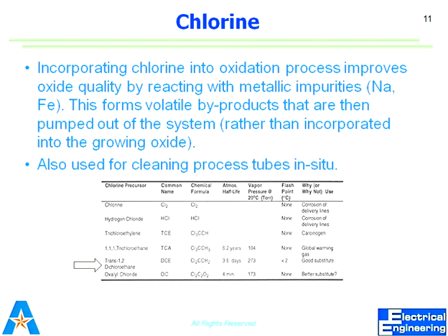You can see that in the last column. Similarly, HCl has the same problem. And if we talk about trichloroethylene, TCE, it was discovered that it can also be used to provide Cl2, that is the chlorine, and it does not corrode the surface. But later on we discovered that it actually causes cancer. It is carcinogenic, which means it causes cancer. So that's why it was banned. So we cannot use TCE.